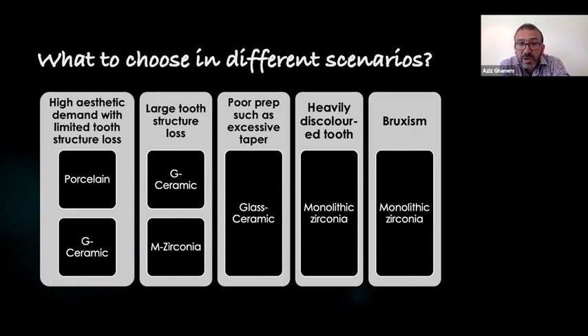For a patient who is suffering from tooth wear, I would go with zirconia, and again monolithic zirconia, because porcelain is more abrasive, causing more tooth wear compared to zirconia. So zirconia is more benign, especially when you've got an antagonist natural tooth. It is less abrasive and kinder to the tooth. But if you use a bilayered restoration, for example zirconia with porcelain on top, we've done nothing, because the facing is going to be porcelain. And again, we've got the same problem, causing more abrasive tooth wear of the antagonist natural tooth.